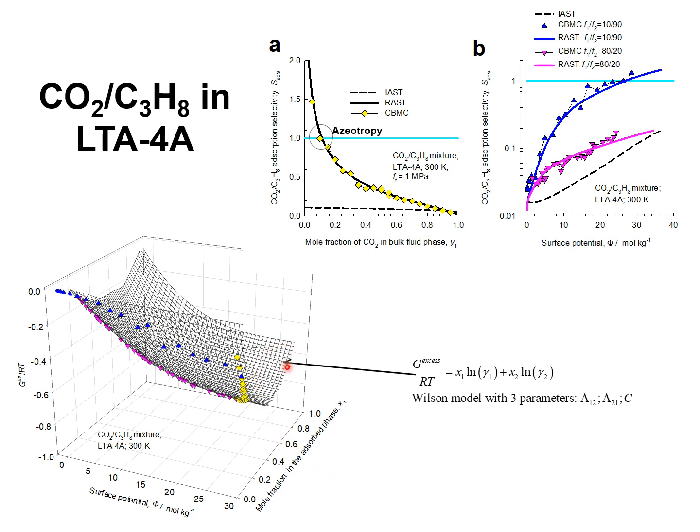We note that the surface has a folded character and resembles a funnel shape, and this is not atypical for mixtures that experience selectivity reversals and adsorption azeotropy.